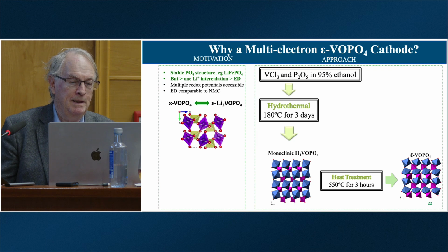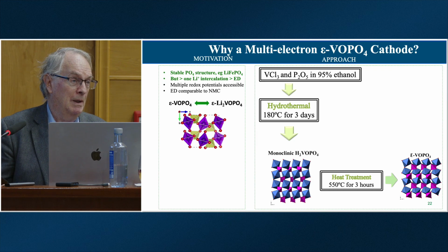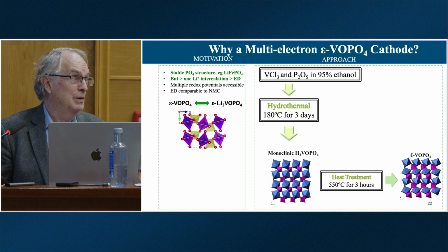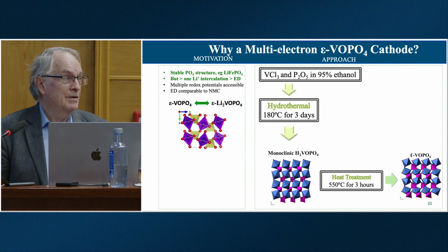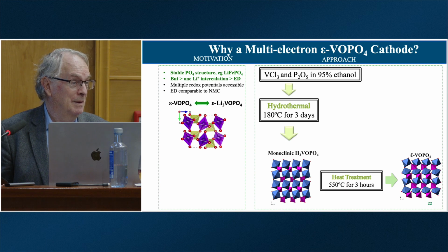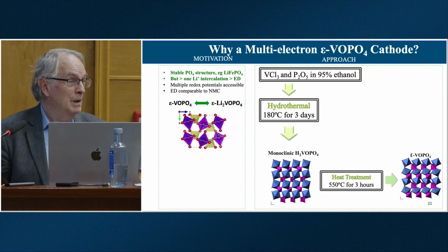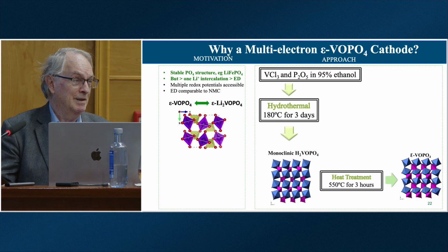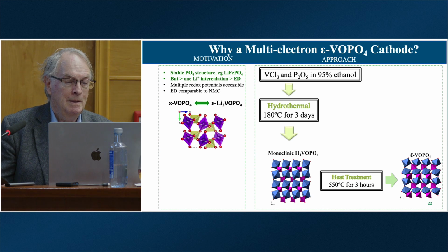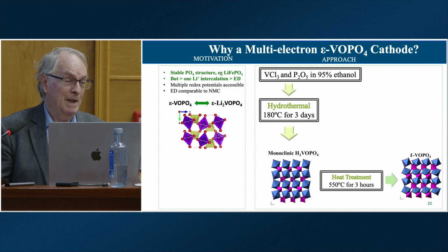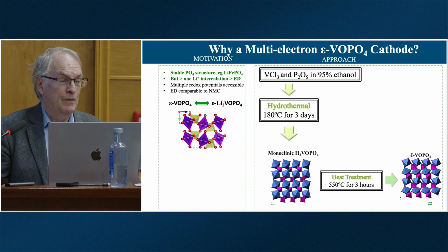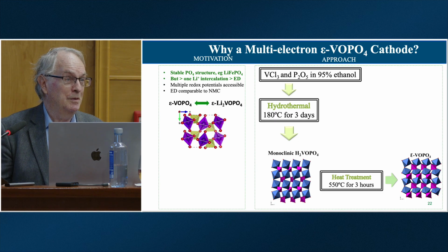So we made these vanadium phosphates using what we call a hydrothermal solvothermal approach. The advantage of that, we do it at about 200 degrees centigrade. It's easy to do in the lab. It's also commercially viable because that's the waste heat in the chemical plant or refinery, so it doesn't cost you anything. So what they did was dissolve all the reactants in basically ethanol with a few percent of water so it didn't reduce too far.